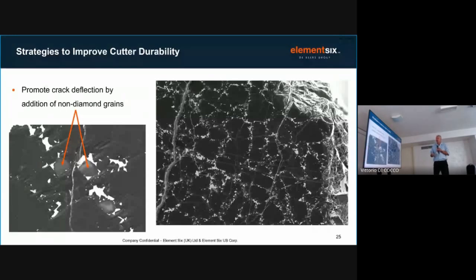Well, if we've got 95% diamond, 5% binder, can we maybe get away with having some non-diamond particles in there? Maybe we only need 93% diamond. So the addition of non-diamond grains, not great contrast there. But you can see here, this is a slightly frustrating picture for me when we saw it. The crack going neatly between the two non-diamonds, completely ignoring our track, if you like. We hoped to see crack deflection and bouncing around, etc. And there's another picture. Not quite sure why I included this, but it's just to give you an overall view where there are so many cracks happening here in this brutal environment.